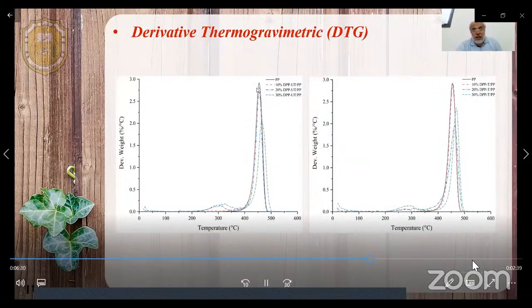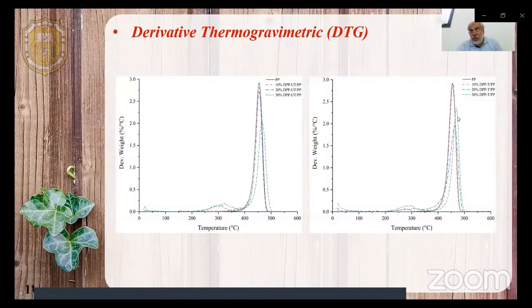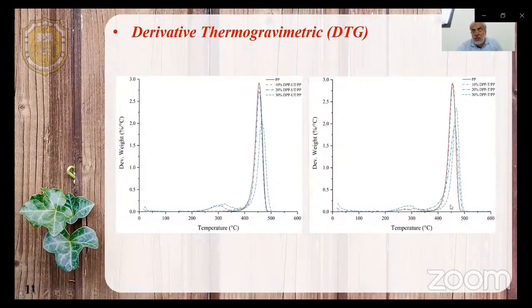So for the thermal analysis, we can see here for the virgin PP based biocomposite, this is for untreated, and this is for treated. When we do the treatment, the peak was shifted to the right, which means that it will burn at a slightly higher temperature, which means more stable. And this peak represents the evaporation of water and burning of other impurities.